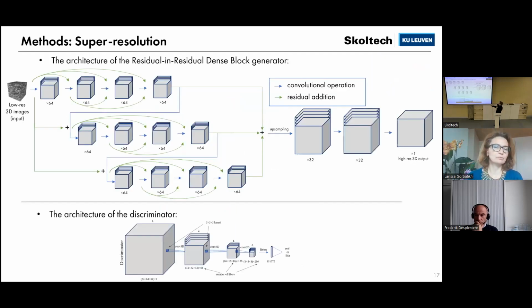So here we also have a lot of convolutional operations, but it only upsamples the data. The main reason why we use residual dense blocks is that at each step the neural network remembers how the image looked in the beginning, and this allows us to rely on the initial image at each step without generating new data, which is not so useful in our case. And the discriminator is quite classical for this type of neural network.